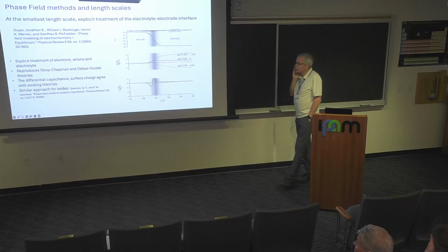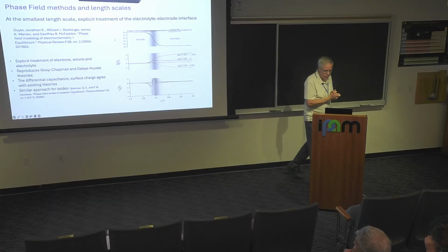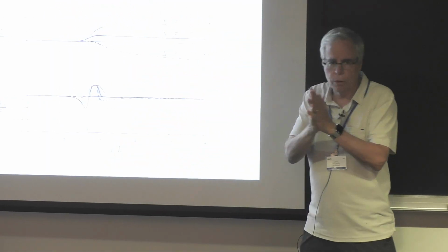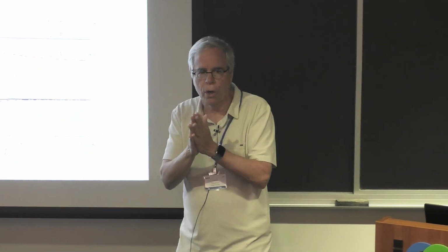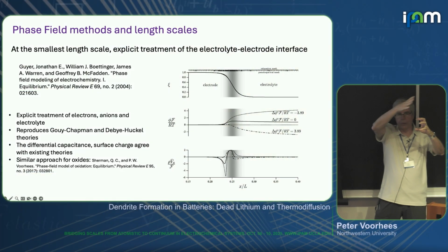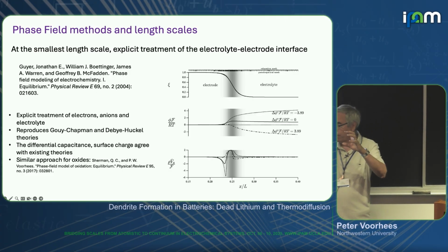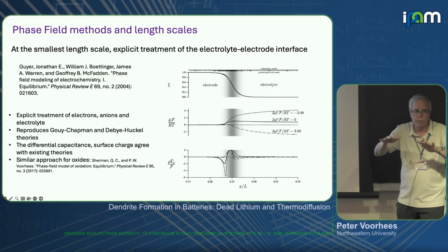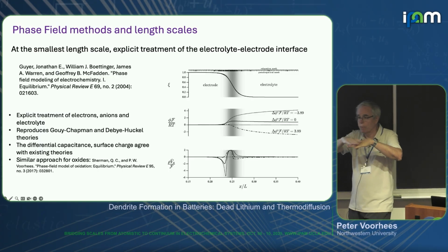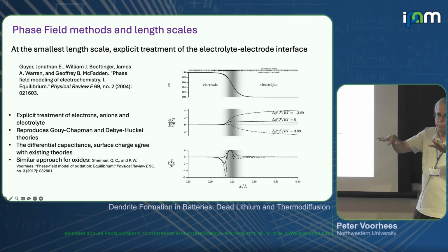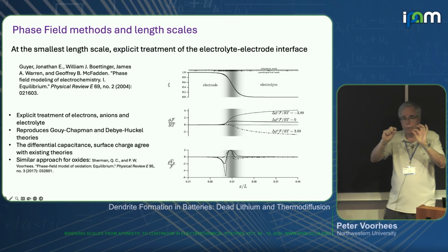All right. So what is a phase field method? For those of you who aren't familiar with the way this works, consider an interface, let's say between an electrode and electrolyte, but this could be a liquid-liquid interface or a solid-vapor interface. Interfaces between materials are almost always diffuse in some sense. Imagine you take two liquids and put them together; they have different compositions, and the composition changes slowly from one phase to another. If you have a solid electrolyte interface, the solid interface is never a completely flat facet. You always have thermal fluctuations. You'll have steps, vacancies, and other things that give rise to diffuseness on some scale.